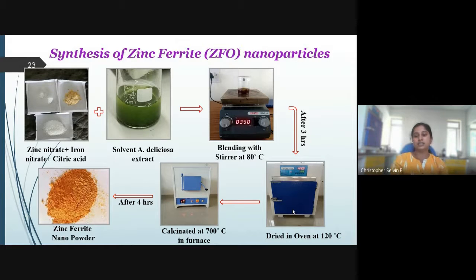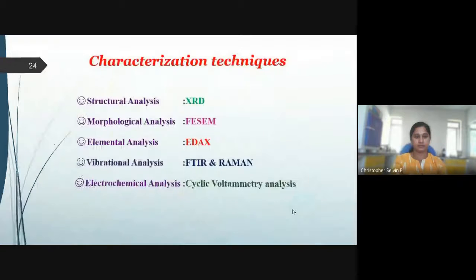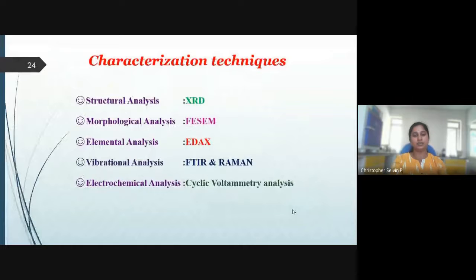After 3 hours, the obtained gel was made into powder by drying in a hot air oven at 120 degrees Celsius. Later on, the obtained powder was calcined in the muffle furnace at 700 degrees Celsius to form the corresponding metal oxides. And after 4 hours, zinc ferrite nanopowders were obtained. These are the different characterization techniques employed for analyzing the properties of zinc ferrite nanoparticles. Results and discussion.